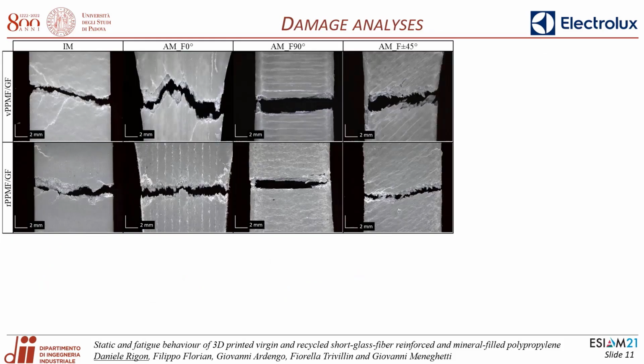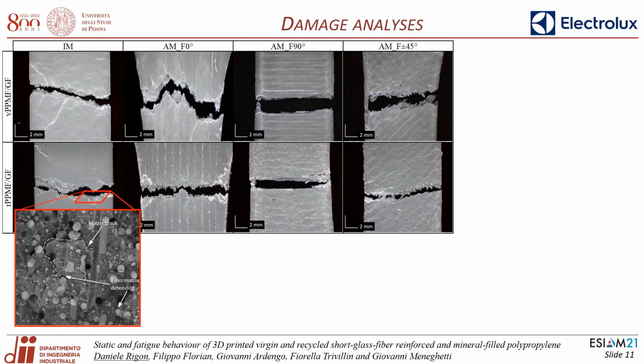Let's have a look now at the damage mechanisms after tensile tests. The injection molded virgin and recycled specimens exhibited similar microscopic failure modes, as reported in the first column of the table, with the fracture surfaces almost perpendicular to the loading direction. This result is consistent with the literature regarding short fiber reinforced polymer composites with mold flow direction parallel to the specimen axis. Analyzing the fracture surfaces, one can see diffuse fiber pull-out, broken fibers, and diffuse fiber-matrix debonding, which probably induce cracks in the recycled matrix.